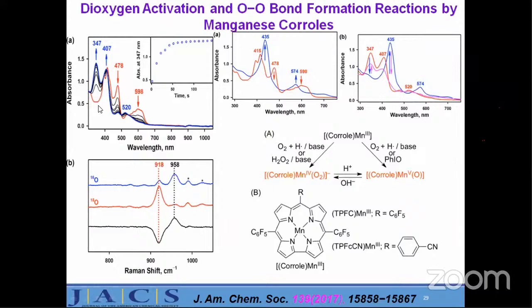Initially these things were observed by doing simple kinetics with UV-visible spectroscopy. You can see here this red color is the starting compound, with a peak shown somewhere at 478. On addition of PhIO, what happens? There is a peak shift, with new peaks formed at 347 and 407, and that is because of the oxo species.